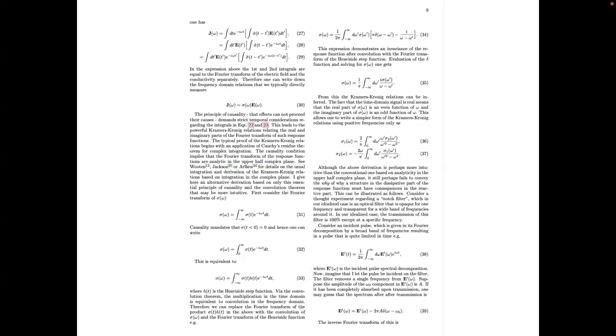Now, I can't measure the delta function because if I try to measure the conductivity at zero frequency, it's infinitely large. So I've got to stay away from zero frequency. But by Kramers-Kronig, I know that if I have a delta function at zero frequency, my imaginary part will go like 1 over omega, with a coefficient related to the strength of the delta function. And this is what's measured all of the time. People will say they've measured the delta function, but in reality they're measuring the superfluid response, coming from this inertial response at higher frequencies. And we can do that because of Kramers-Kronig.